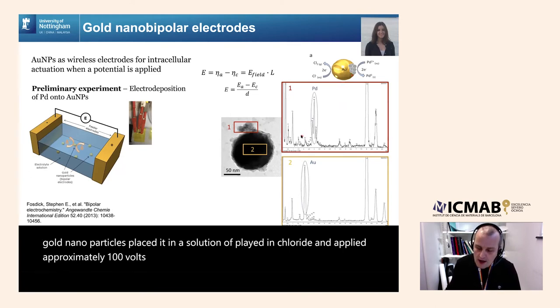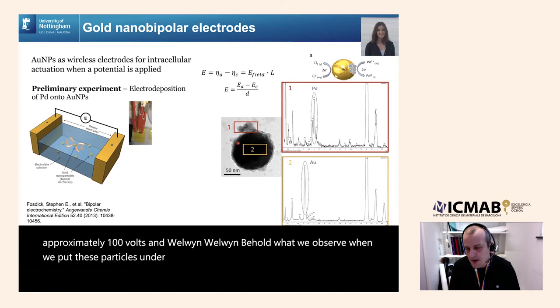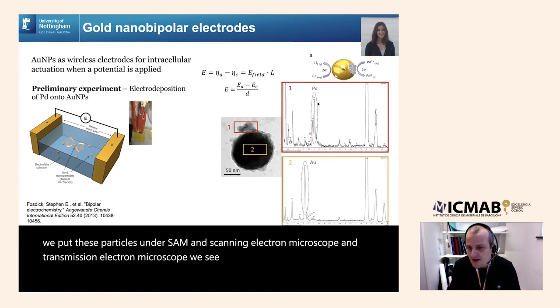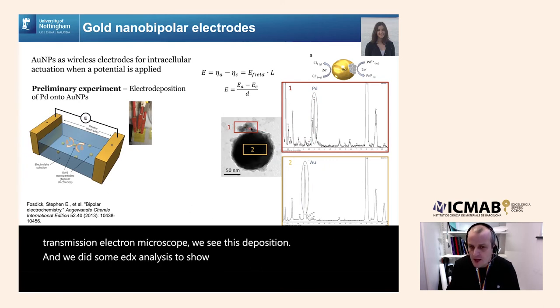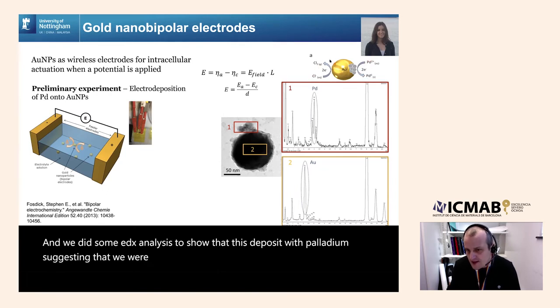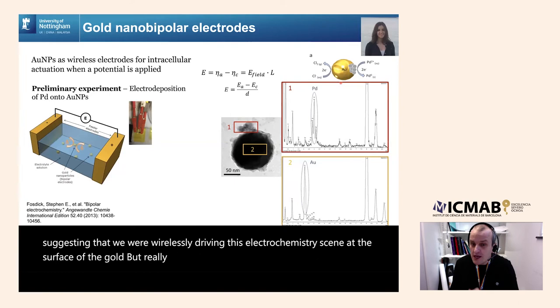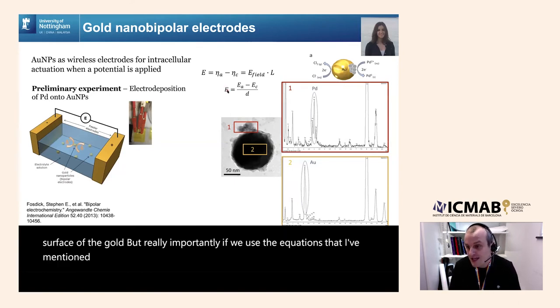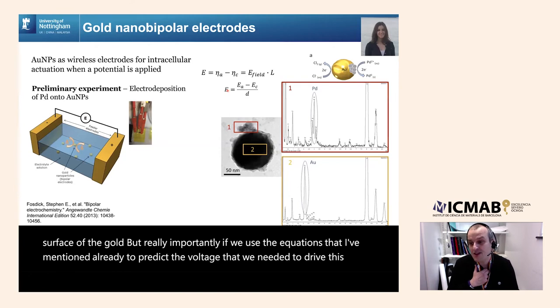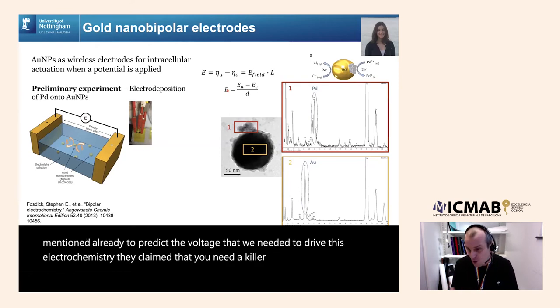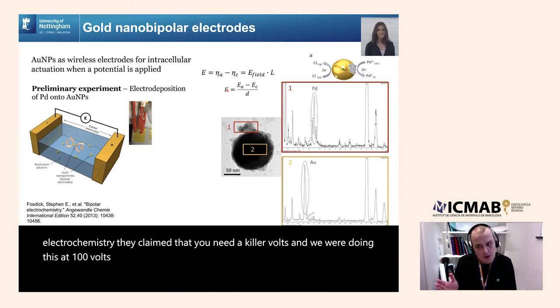And lo and behold, what we observed when we put these particles under a scanning electron microscope and transmission electron microscope, we see this deposition, and we did some EDX analysis to show that this deposit was palladium, suggesting that we were wirelessly driving this electrochemistry seen at the surface of the gold. But really importantly, if we use the equations that I've mentioned already to predict the voltage that we needed to drive this electrochemistry, they claimed that you needed kilovolts, and we were doing this at 100 volts. So clearly still quite high, but much further away from what is theoretically proposed in the literature.